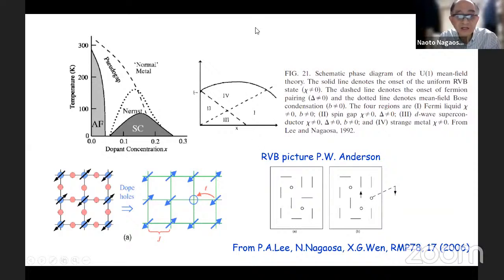So this is a typical phase diagram based on the RVB picture of P.W. Anderson. The physics of the cuprate is believed to be described by this square lattice tight-binding Hamiltonian with a copper site occupying the corner of the square lattice. And at the bond positions, you have oxygen, right? So actually, once you dope holes, this vacancy can travel. And on all the other sites, you have a magnetic moment of spin 1/2.